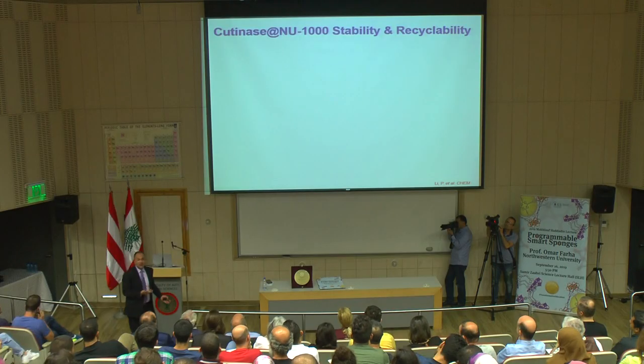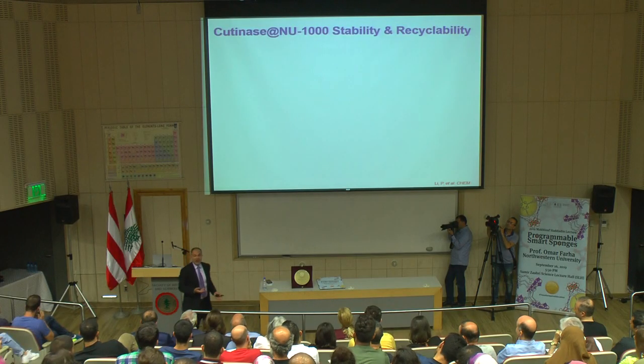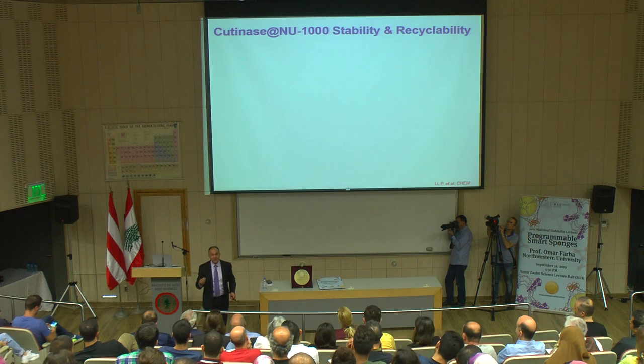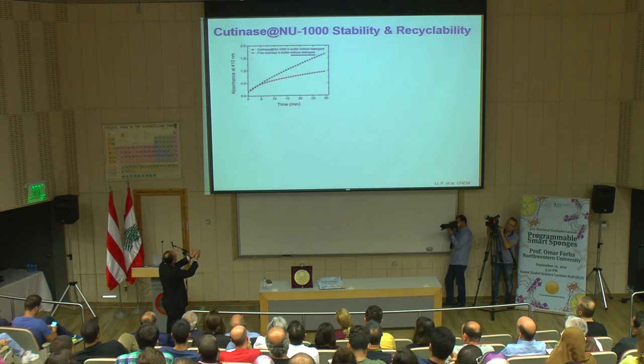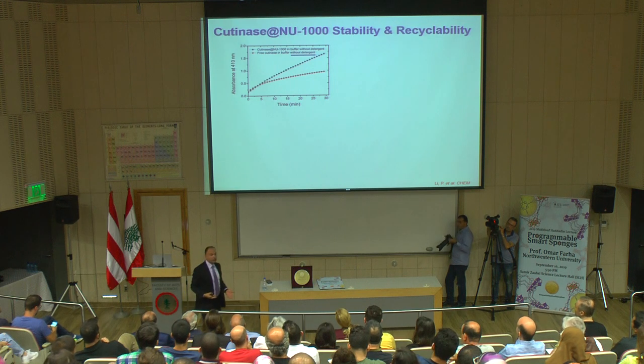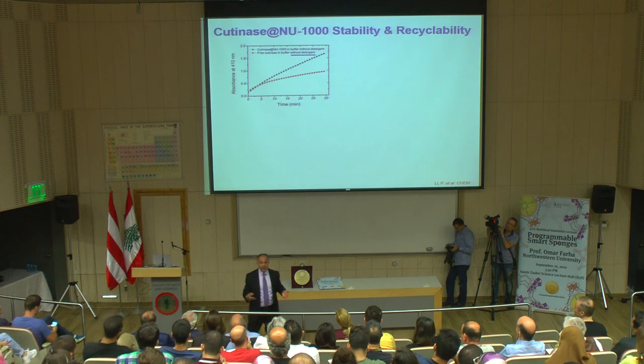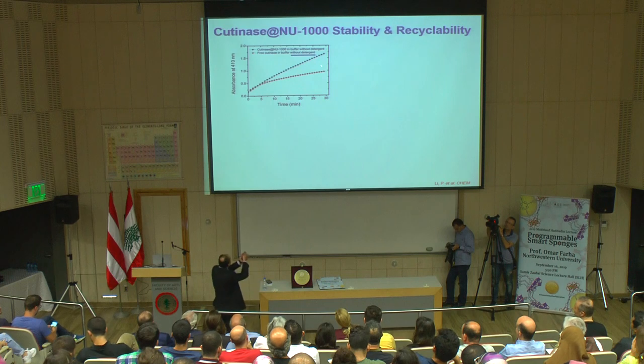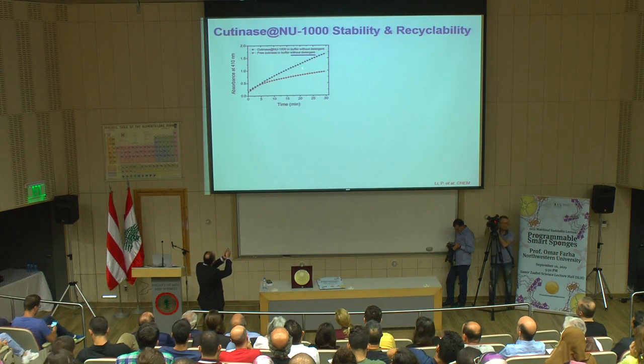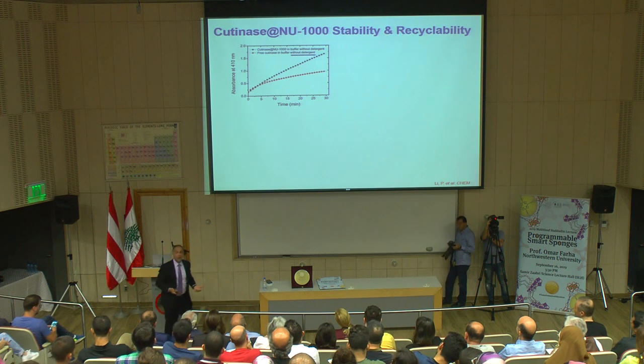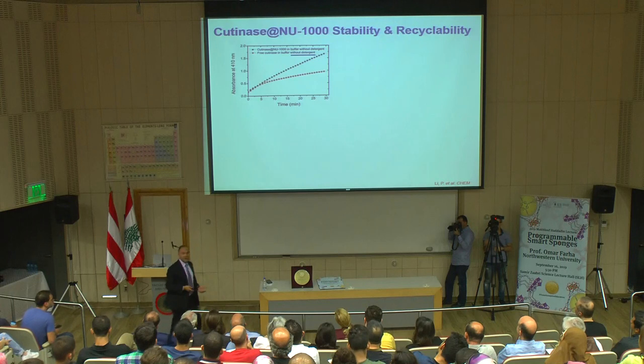But I told you we know this enzyme does this reaction, but did we make it more stable than the way we started with? So this particular enzyme likes to be around detergent because otherwise it aggregates and precipitates. You could see if we do this reaction without detergent, the composite is doing a lot better than the free enzyme. But you might argue, okay, Omar, you increased it a little bit. Who cares?